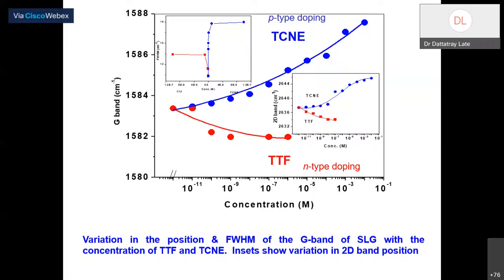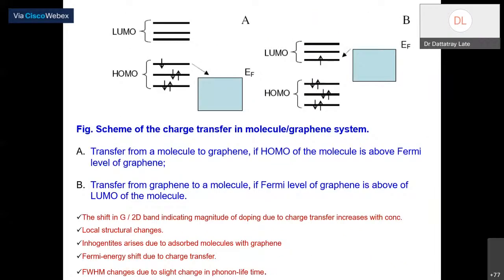This is because we're adding the concentration, so the degree of dopant is also changing, and because of the changing degree of concentration this gives you a slight change in the opening of the band gap, and therefore this becomes slightly more P-type, and this becomes slightly more N-type behavior of the material. Again,